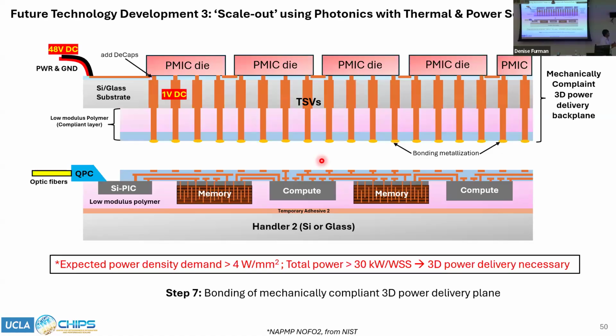And then what you can do is deliver the power. If you see here, when you're building these large scale systems, a single 300 millimeter wafer, you can estimate that the power consumed can exceed around 30 kilowatts per wafer scale system. So you're looking at a power density of more than 4 watt per square millimeter typically, right? So the only way you can deliver this power is using some kind of 3D way of delivering the power, basically vertically delivering the power.